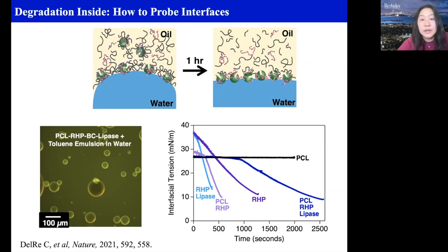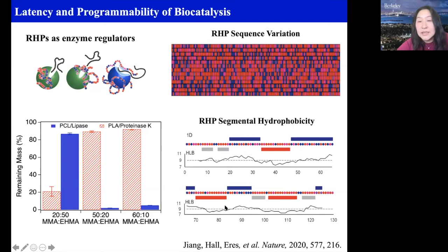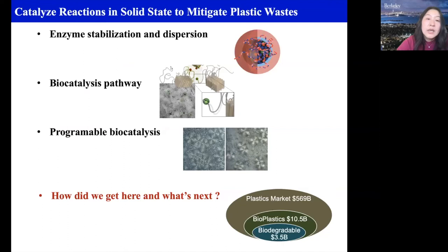So let me just walk you through here. This really goes back to the design of the wrapper. One is going to cover the active site. One is going to make the active site available. But nevertheless, in this case, we are particularly looking at the PLA and proteinase K combination. And basically by screening different wrappers, we can get the PLA to either not degrade or have it degrade fairly rapidly. All right, so that is, I would say, in the very early stage of our journey,